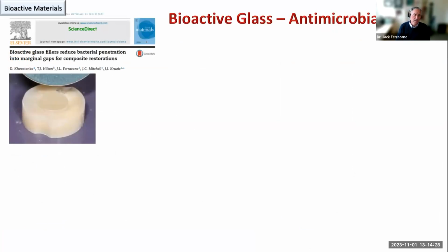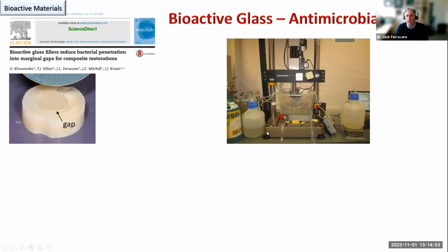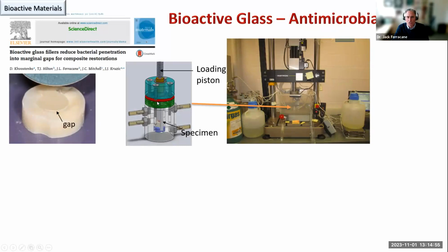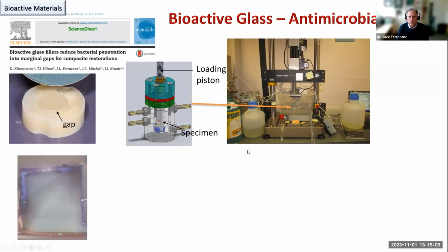So to just show you an example of some things we've done with this in the past, looking at bioactive glass, can it actually inhibit bacteria from progressing down a gap? So this is a dentin disc. We drilled a prep into it. We put composite, but not bonding it on half. So this is a gap formed in here. And we did this with different sizes of gaps, basically put it into a complex bioreactor system so that we mechanically loaded it after we had formed a biofilm on the surface and kept the biofilm alive, and to see what the bacteria does to this interface.